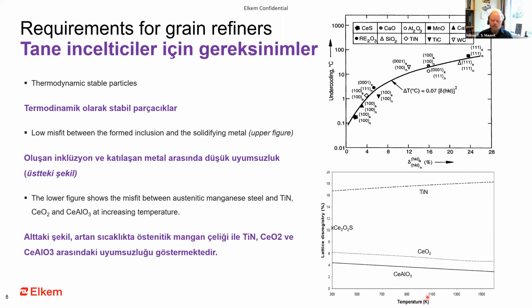So for the wear-resistant manganese steels, the old-fashioned grain refining has been to add ferrotitanium to promote titanium nitrides, titanium carbides, and titanium carbonitrides. Well, what we actually see is that titanium nitride has a quite high degree of misfit between the austenite matrix and the titanium nitride itself. And it's increasing with increasing temperature. So essentially, it will take a lot of undercooling for titanium nitride to be able to be a nucleus for the solidifying steel. While a cerium oxide or even cerium aluminates should be far better as a nucleus, because they have a very low disregistry, and it's even decreasing as the temperature is increasing. And we also see that cerium oxysulfides have a quite good disregistry.